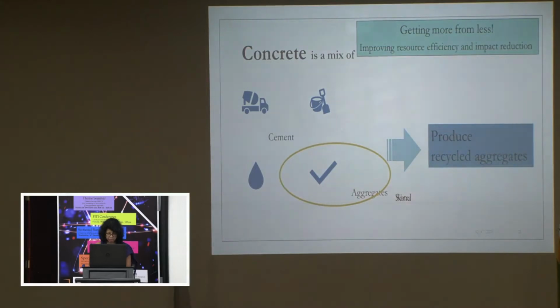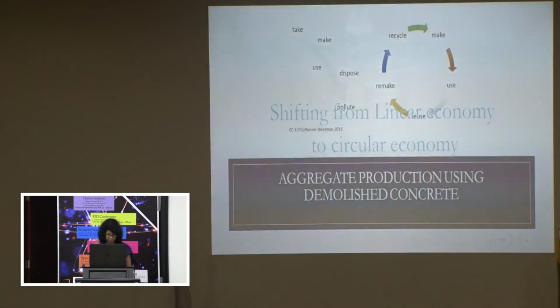Research has shown that it is possible to substitute cement with alternative byproducts from different industrial processes such as fly ash, rice husk ash, and slag, with positive impacts. Aggregate constitutes the bulk of concrete. Therefore, effective use of recycled aggregates will lessen the demand for virgin material. Although the reuse of demolished concrete to produce fresh concrete began as early as 1945, much remains to be investigated.